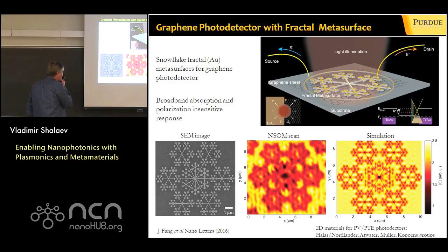In our group, my student Di Wang, along with Gerard Fan, did work on how to make this photodetector really efficient. And the idea they used comes down to my early work. I have been working for a long time on fractals, and fractal structure, which is a scale invariant structure. Because of their scale invariant symmetry, they promote localization. So if you make a plasmonic structure with fractal geometry irradiated with light, then excitations tend to be localized in very small areas called hotspots.